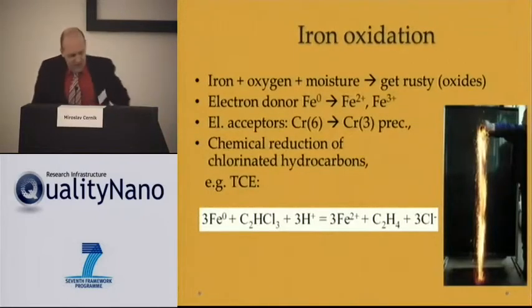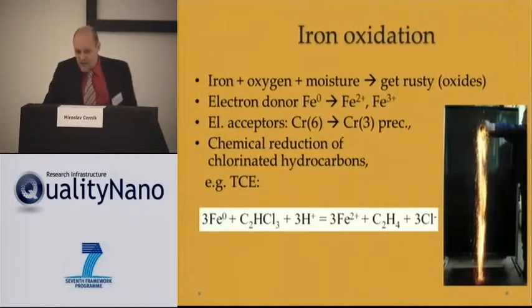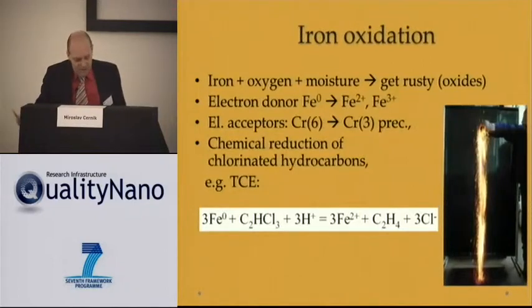So, in general, the reaction is simple. We take the iron, like we have the microscale iron, it reacts with oxygen and moisture and gets rusty, gets oxidized. In general it's a donor of electrons, and we have some electron acceptors, which can be oxygen, or in our case some contaminants like chromium-6. Chromium-6 is chemically reduced to chromium-3, which precipitates, and the water is clean.